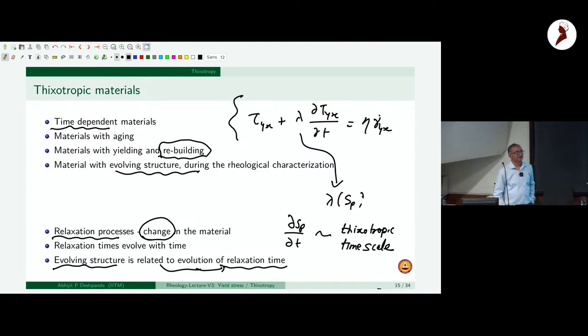So this evolution, is it under shear or just like? No, so the one key feature is that this is a function of the rate constants of rebuilding and reformation, but it's also a function of the shearing of the system, the deformation. So that influences. And presumably it's easy for us to justify that breakage is affected by the shear rate, but you could also have reformation affected by shear rate. Of course, you would have a Brownian term which leads to reformation, but you can have a shear-induced reformation also. So the rate terms in this equation can be related to the shear rate.